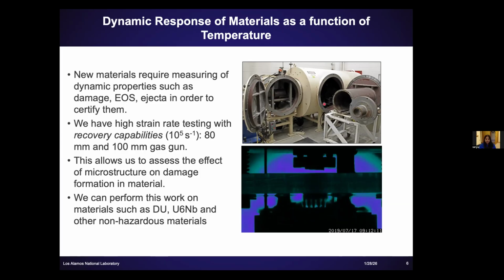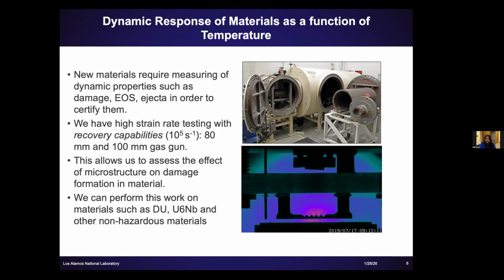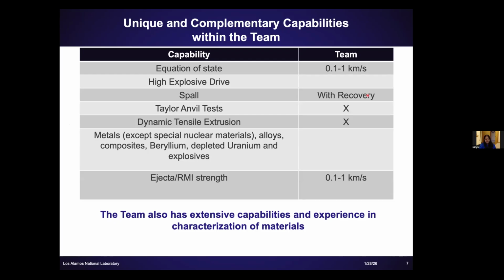So this is one of our recovery chambers on an 80 millimeter gas gun. Essentially, this is the small tank that goes into the big tank. After our sample gets impacted, we soft recover it within this tank. Then we can section it and look at, okay, well, the material failed here, here, and here. Perhaps if we modified the microstructure in A, B, and C ways, we can improve the dynamic properties of this material. So that's the unique thing that my team does. I like to joke that most of the people in my team are actually material scientists, and we just look at shock as a way of subjecting your materials to some interesting loading conditions to see how they fail. That's why we also have that low velocity gun, which a lot of people don't tend to have. Here is just a table showing our capabilities.